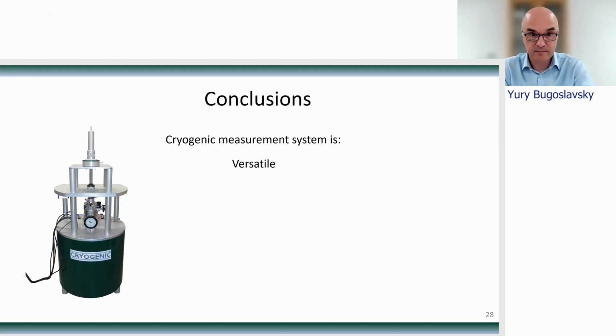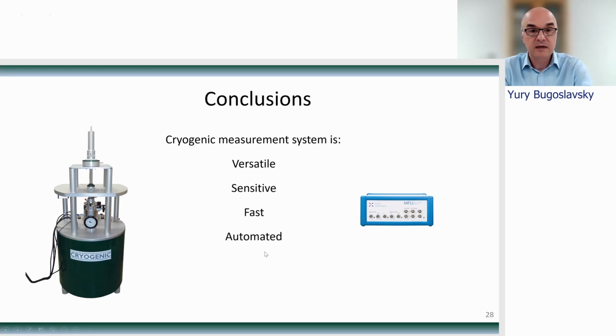It is versatile. It is certainly sensitive, and the key part in the sensitivity of the machine is played by using modern, fast, highly sensitive electronics. The system is fast compared to other high sensitivity systems. We can use relatively fast ramp rates of magnetic field and temperature and so on. The system benefits greatly from a high degree of automation. In the cryogen-free system, the variable temperature insert can run practically indefinitely, and you can program your measurement sequences to run as long as you need to collect your complete set of experimental data.